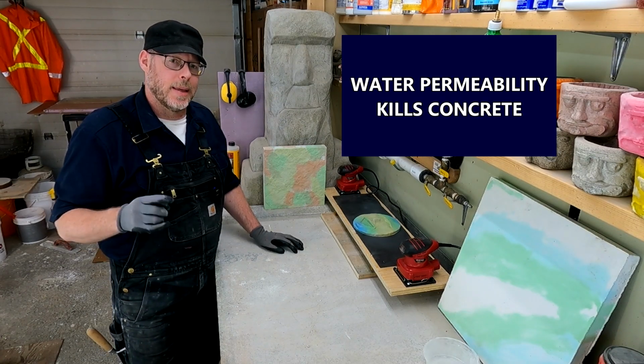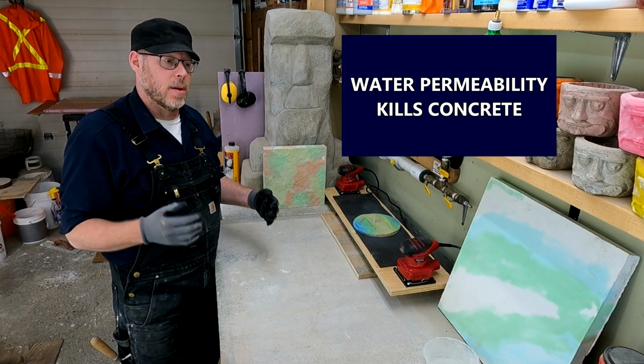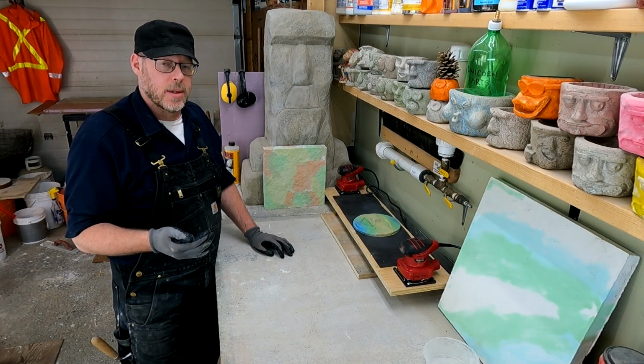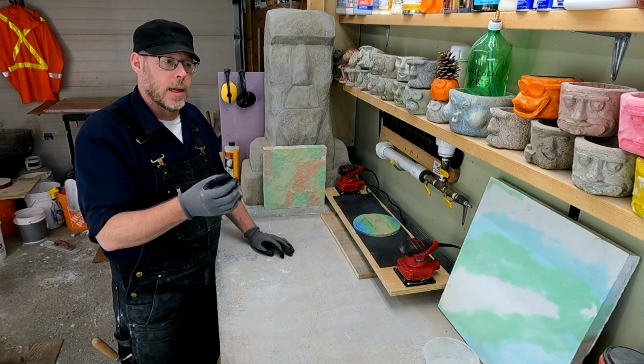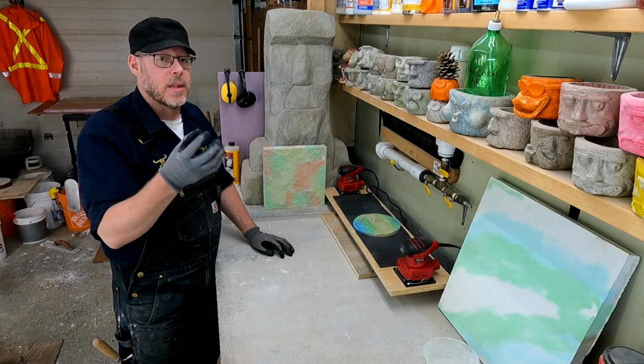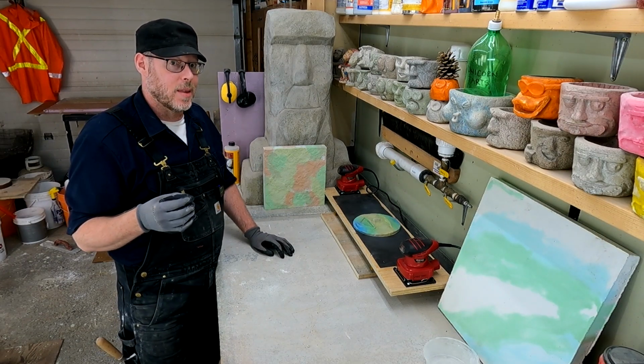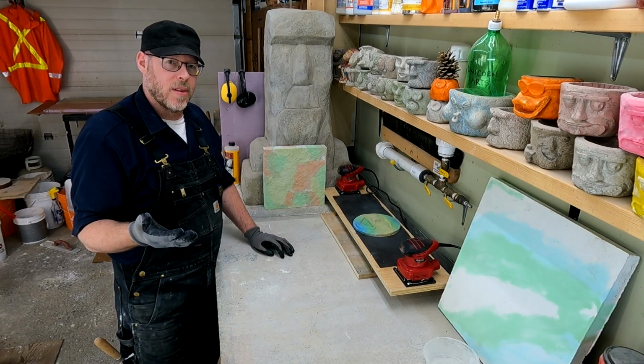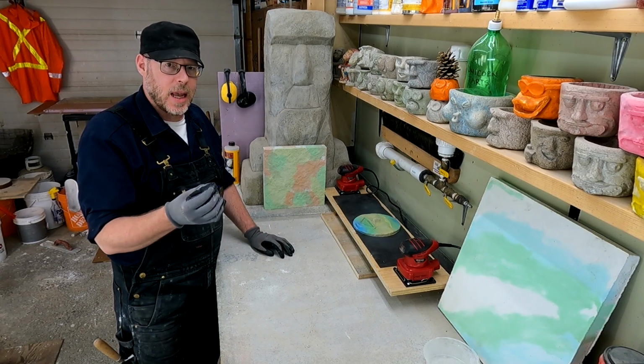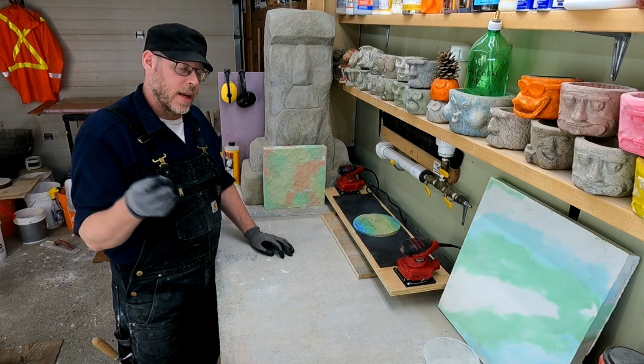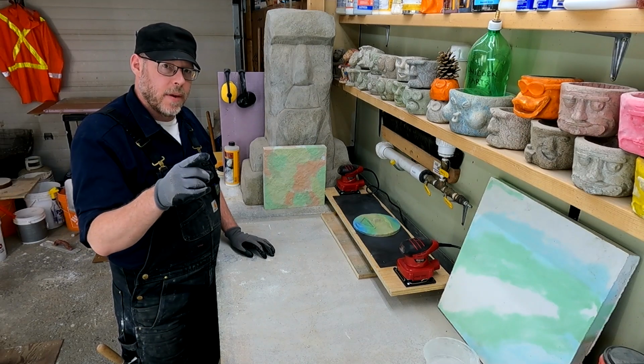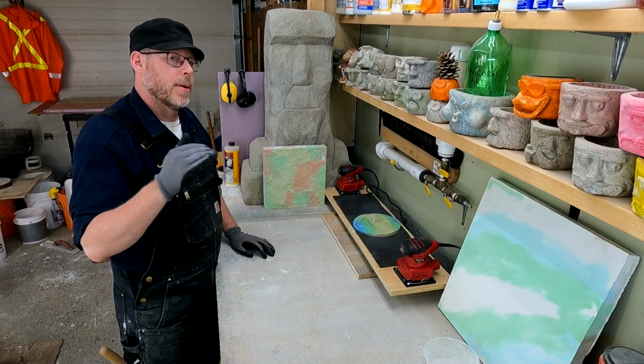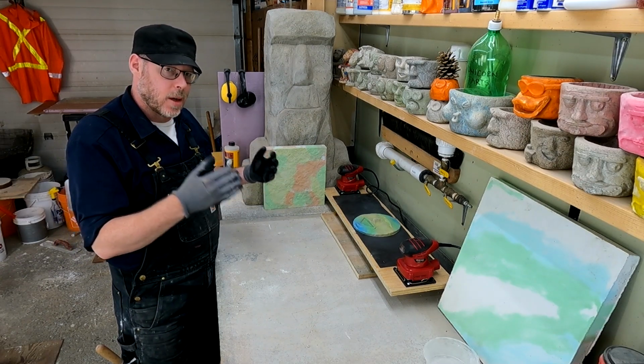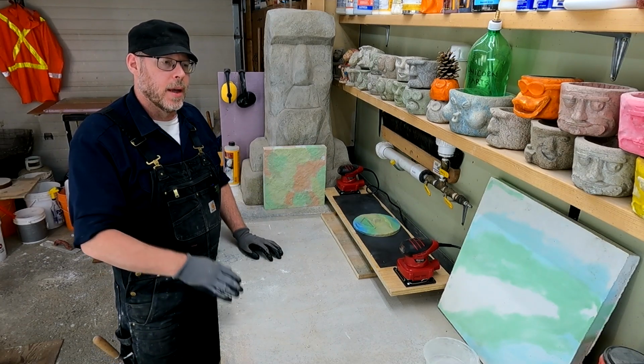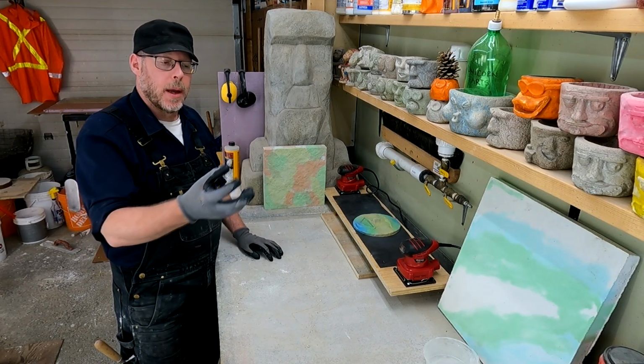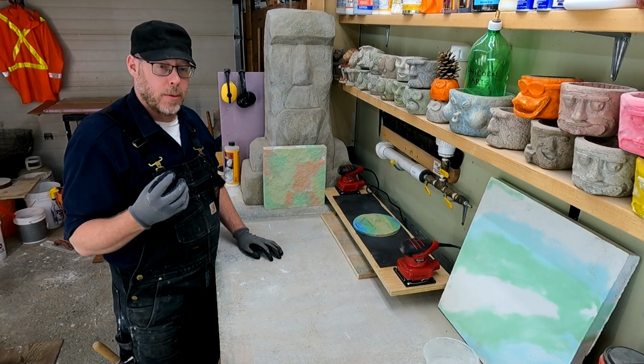Water permeability kills concrete. This is what kills concrete. Very slowly over time, as water passes through concrete, the Portland cement component will dissolve and pass along with that water, leaving behind only the aggregates, a rough, sandy, weakened surface. And that's exactly what happens. So you have a dry, sandy, porous surface to your concrete slab that you've dry poured, it's basically a big concrete sponge. It's going to absorb water very readily.